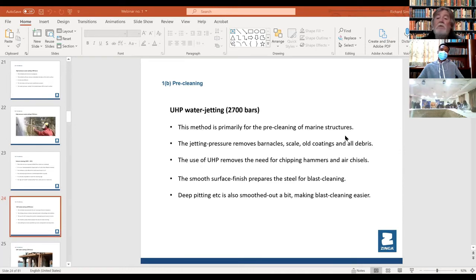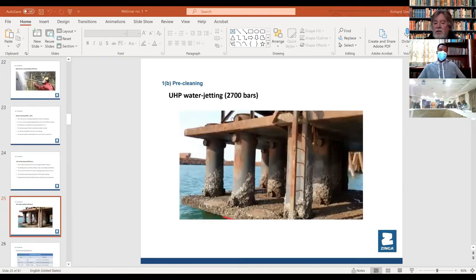So on some jobs, especially near the coast, if you're doing jetties in the sea and so on, this is the best method, because it blows off barnacles, shellfish, old scale, oil, everything. It takes it all off in one go. So this is by far the best before you do sandblasting or blast cleaning. This is one of the best for all marine work. It's exceptionally good. You can see there all the shellfish on the steel work here at low tide. It'll take off all that, all the loose rust and all the mill scale will be completely removed, ready for blast cleaning.